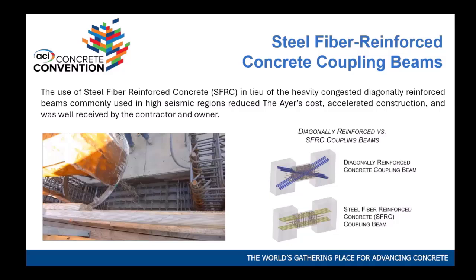It's about 160 pounds of fiber per cubic yard. It's a very healthy fiber dosage, to 200, depending what we need. But what happens is you reduce the rebar in that beam by about 40% from a typical beam. So it's much easier to place. You don't have the diagonal that clashes with the top rebar coming down. So it turns out to be a very constructible tool that streamlines the rebar of the core going up the building.